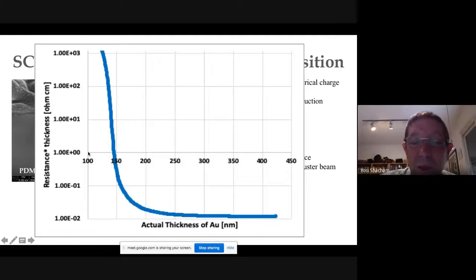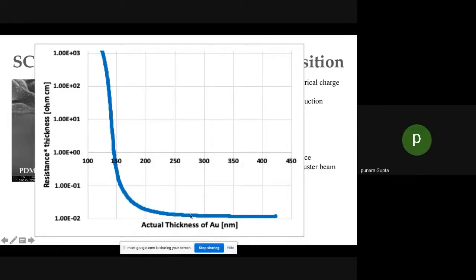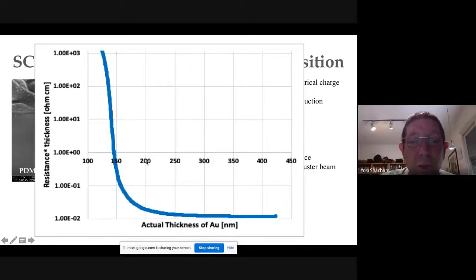Above 100 nanometers, the resistivity goes down from 1 kilo-ohm centimeter to 10 to the minus 2. The resistivity goes down by 5 orders of magnitude. And you can use it, by the way, to measure position and to measure stress. So if we deposit 200 nanometers of gold, we can have a good electrode, because it's flexible like PDMS and conducting, not like pure gold, but 10 to the minus 2 is a pretty good conductor.